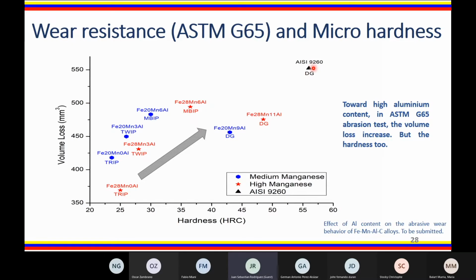According to the calculation of the stacking fault energy using a thermodynamic model with the chemical composition, the mechanism that possibly predominates in the dislocation movement in steel with low aluminum is TRIP. With the increase in aluminum from 3 to 6, the mechanisms that are possibly present are TWIP and MBIP, and with a high aluminum content, the governing mechanism is possibly dislocation glide. It is also interesting to appreciate that the increase in the aluminum content generates hardening of the steel. See the hardness of the materials. It has the role of increasing the strength of the material by solid solution.